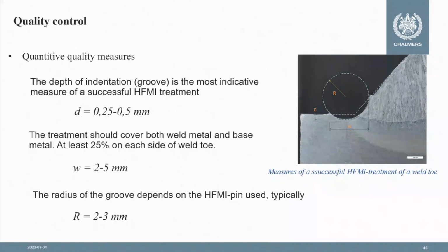It is also important to make sure that treatment covers both the base metal and the weld metal. So this length W should be something between 2 and 5 millimeters, and at least 25% of this is positioned then on either side, either the weld side or the base metal side. As to the radius of the groove, it depends on the pin used. Typically 3 or 5 millimeter pins are used for weld toe in general.